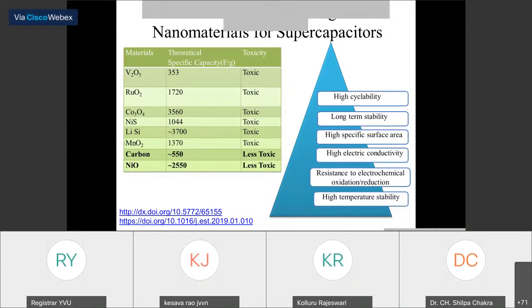Basically, we have a lot of materials where people are also working on: vanadium oxide, ruthenium, cobalt, nickel sulfide, lithium silicide, or MnO2. But we are mainly focusing on two main materials here, carbon and nickel oxide, because these are non-toxic. So our target is the toxicity, because toxic materials can affect the environment. So we wanted environmentally friendly materials to be used to develop a supercapacitor or an energy storage device. These materials will have high cyclability and long-term stability. It has high specific surface area because we have carbon in it, it is highly conductive, it can have resistance to electrochemical oxidation reduction, and it has high temperature stability also.